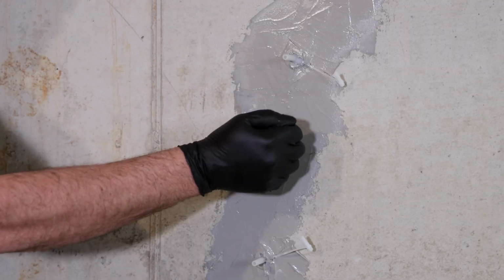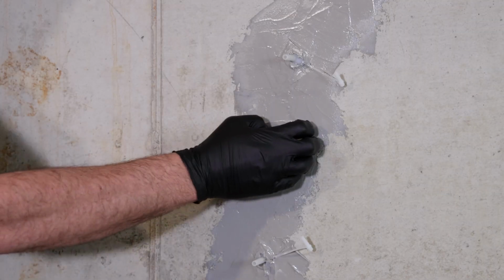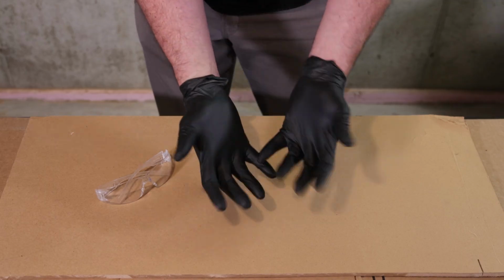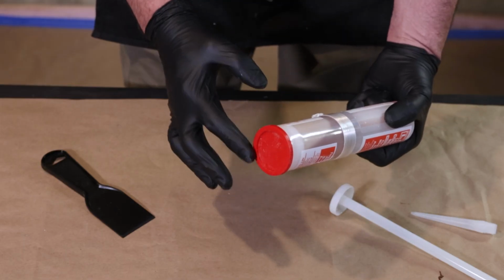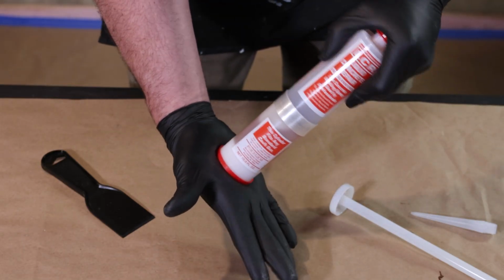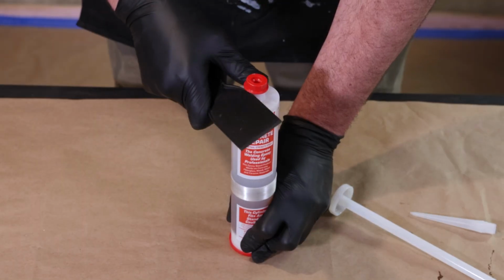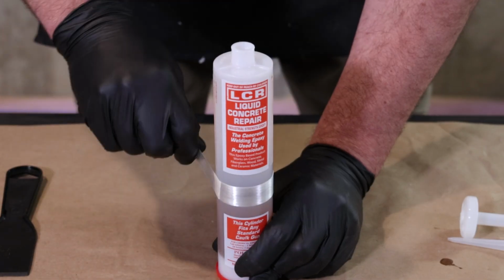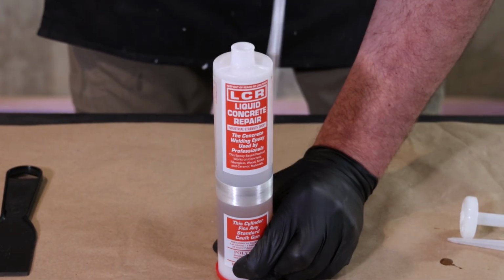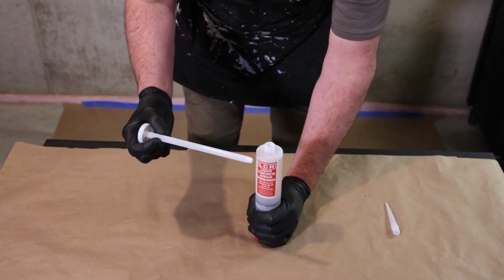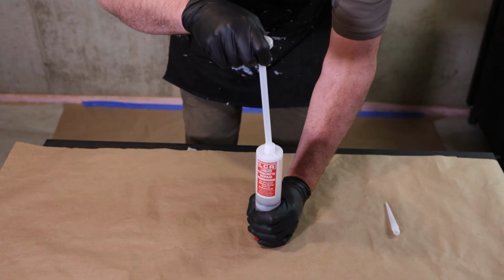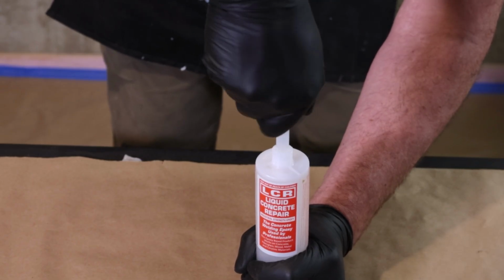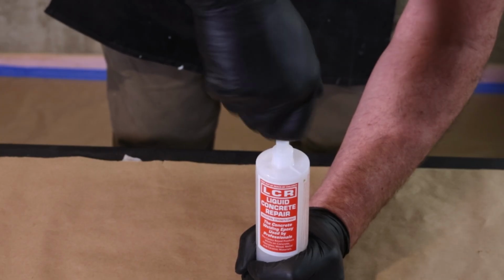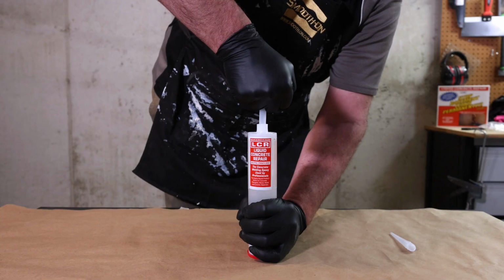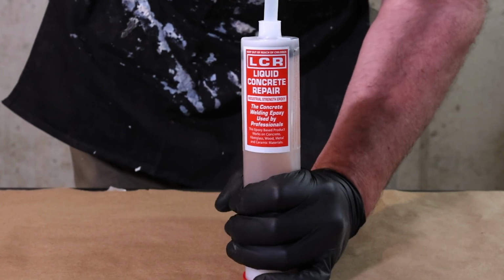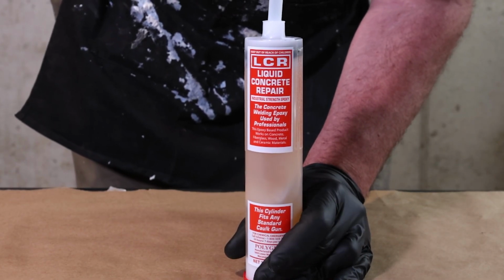After the paste is fully cured, you can begin resin injection. Be sure to wear disposable gloves and safety glasses. Start by checking the cartridge assembly. Make sure the red cap on the bottom is secure, then remove the small red cap at the top. Next, remove the tape wrapped around the cartridge. Insert the mixing plunger into the top opening. Hold the cartridge at the midpoint to keep the internal mixing wheel from moving, and thread the plunger clockwise until it stops. Then, while holding the cartridge firmly, pull the plunger sharply upward to rupture the foil barrier inside.